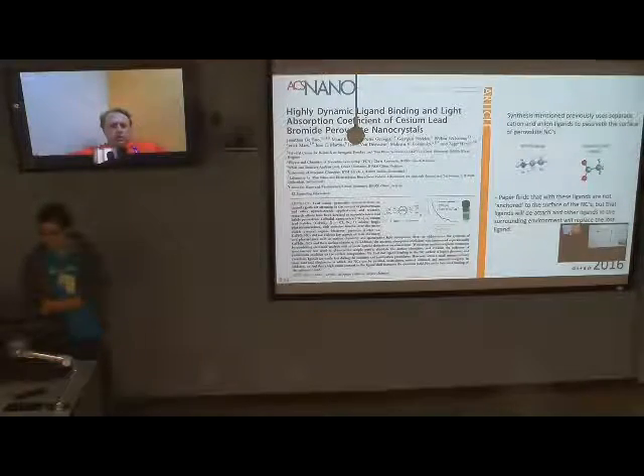Yeah. In case of cadmium sulfide or whatever, the semiconducting quantum dots which you are working with, again, if we're talking about neutral ligands such as amines, phosphine oxides, they're neutral, and even silanes. So that's why it does matter. And it looks like they bind stronger to the metal sites, because again, we understand due to the dipole-dipole interaction, you have nitrogen attached, of course, not to the sulfur, but to the cadmium, right? But if we have ionic ligands, we again have to balance it by going to the non-stoichiometric structure of quantum dots. And I think in his case, he just put in two types of ligands to balance the charge.